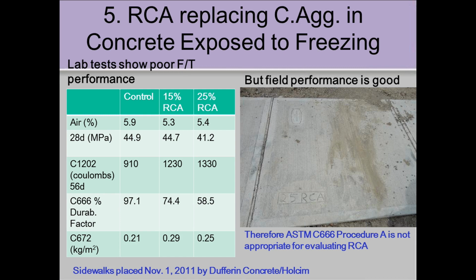Not the de-icer scaling performance, but the freeze-thaw, because you take small beams, 3-inch cross-section beams, you put these porous aggregates in there, the concrete is fully saturated from when you cast it till you start the freezing cycle at 14 days, and it never dries out. So in that case, those porous aggregates act like porous aggregates that are fully saturated, and they break apart. So it's an artifact of the test procedure.